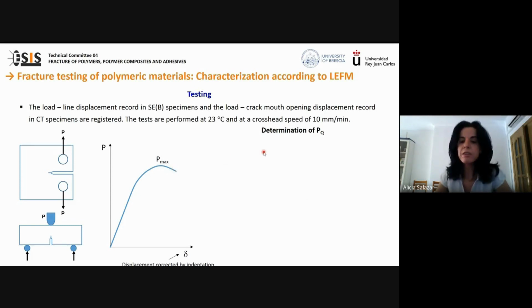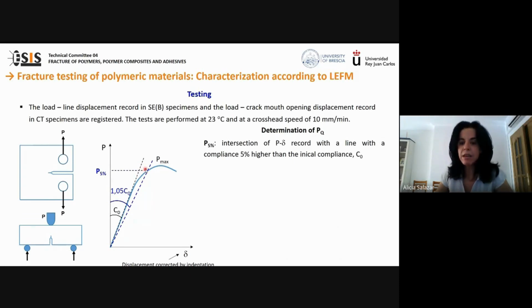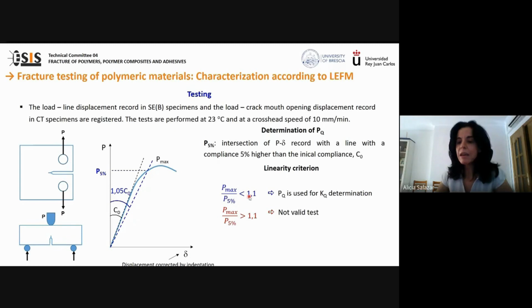For this, it is first necessary to calculate a conditional result, KQ, which is obtained from a load named PQ. And to attain this load, the following construction on this test record is needed. First, draw a best fit line to determine the initial compliance, C0, dotted line in black. Secondly, draw a second line with a compliance 5% greater, dotted line in blue. And the intersection of this straight line with the load curve is defined as P5%. If the maximum load over P5% is smaller than 1.1, the linearity criterion is fulfilled. Otherwise, the test is not valid.